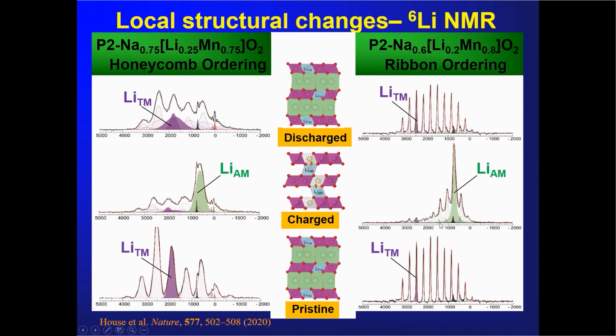I'm going to skip one or two of these in the interest of time, but this is some lithium-6 NMR, and I just draw your attention to this feature on the right. This is the ribbon structure. Here is the resonance for the lithium in the transition metal layer. Here is the lithium in the alkali metal layer. So when you take sodium out of this compound, the lithium in the transition metal layer drops into the alkali metal layer. Then when you put the sodium back in, the lithium pops back again into the transition metal layer in the same position. So there's reversibility here, whereas over here you can see the purple is rather different, representing the lithium now in a different environment.